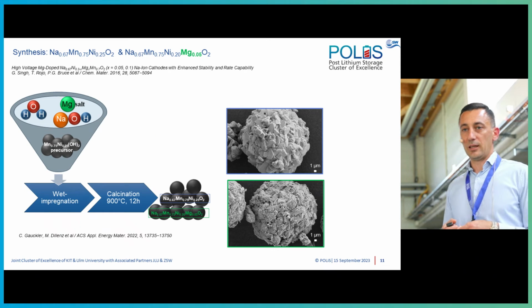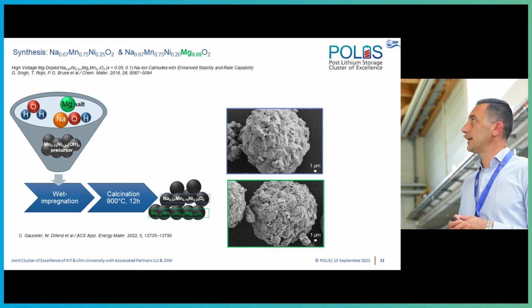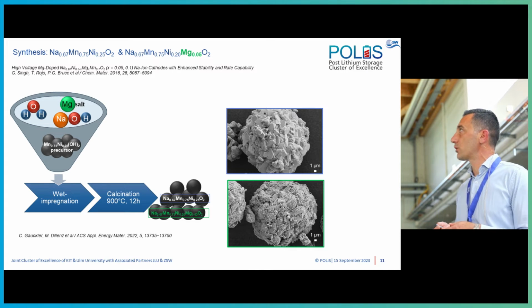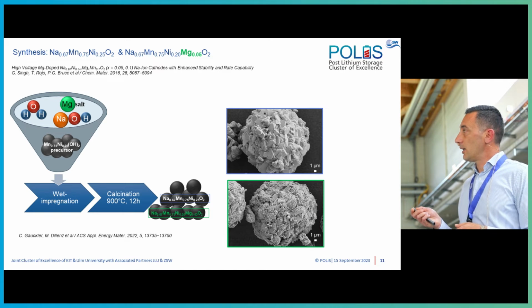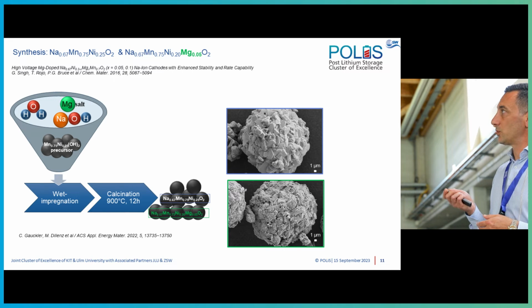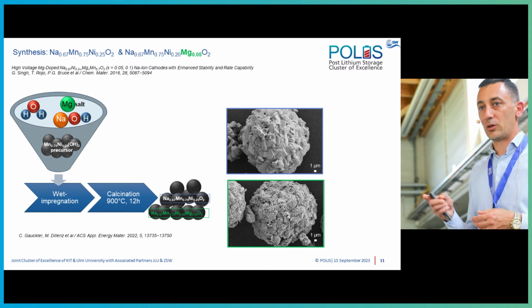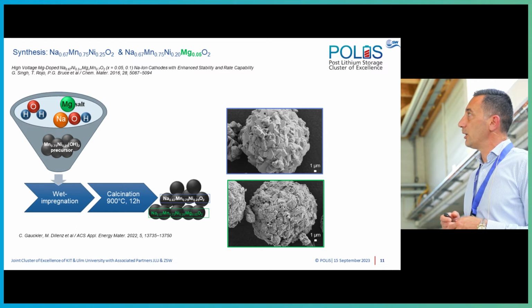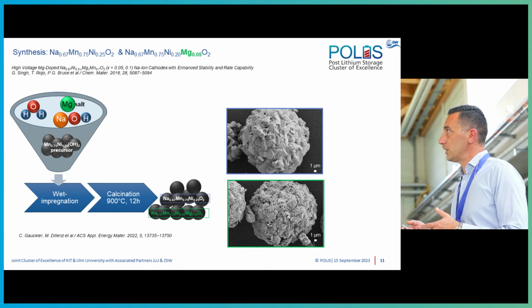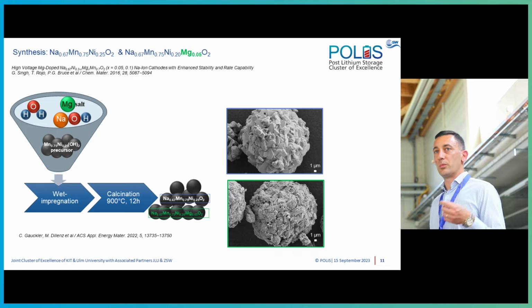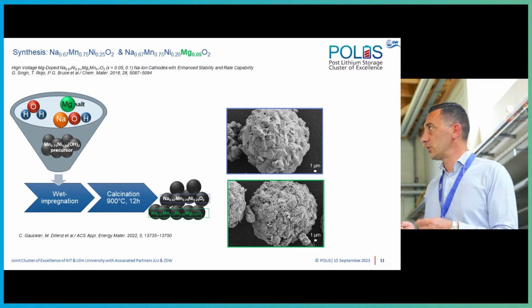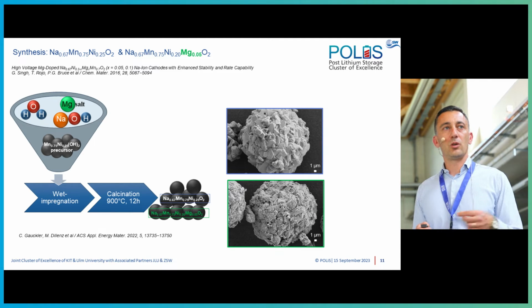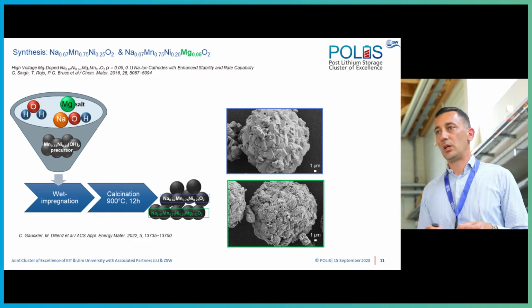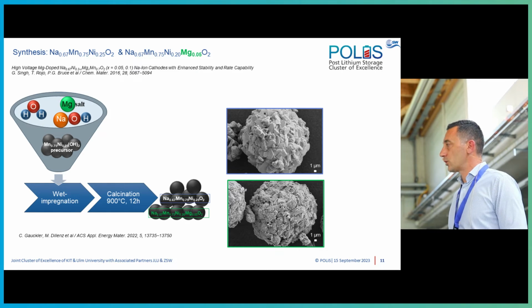So to synthesize the magnesium-doped sodium manganese nickel oxide, please note that the level of doping is relatively low. We looked first in the literature, and this was a publication we saw, from Teófilo Rojo and Peter Bruce, published a few years earlier, where they already investigated the influence of the magnesium doping in a very similar structure. Of course, then the synthesis was all solid state, so the particle morphology couldn't be controlled as well as we can actually do.